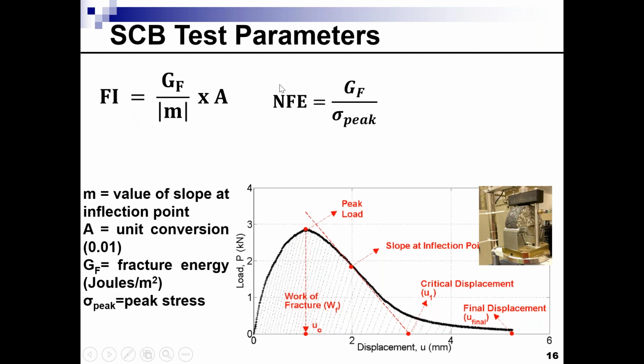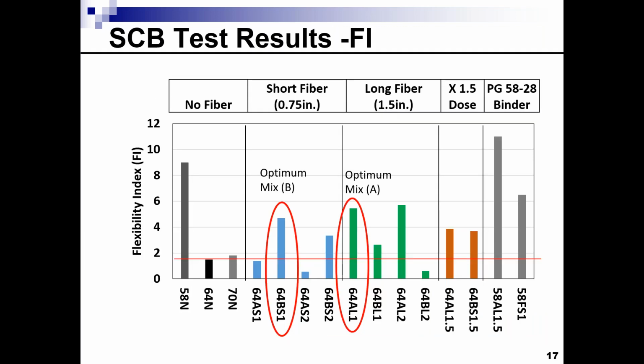We have also used a normalized fracture energy. I will not be going into that in detail, but this is another parameter that was suggested based on previous research work that I have conducted, which is basically the fracture energy normalized by the peak stress. So for the SCB, those are the results of the flexibility index.